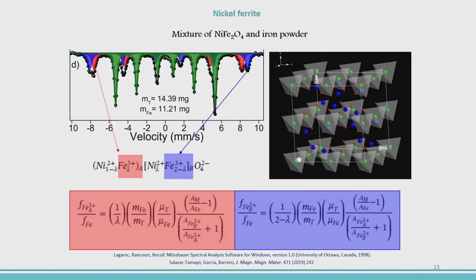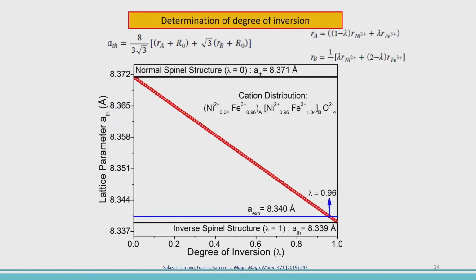So lambda has to be determined also independently. So how do we determine this? We simply take the X-ray diffraction, and we determine the lattice parameter, and then we use this formula that is already known in the literature, and we assume explicitly here that nickel can be at both sites, tetrahedral and octahedral, and we just simply compare. This is the theoretical line, and we just see where it cuts here, where is the crossing. This is the experimental value obtained by using Rietveld refinement of the X-ray diffraction, and we just get the value of lambda. We need the value of lambda, and then with this lambda we can go to the previous formula and just replace, and we can get the recoilless factor.